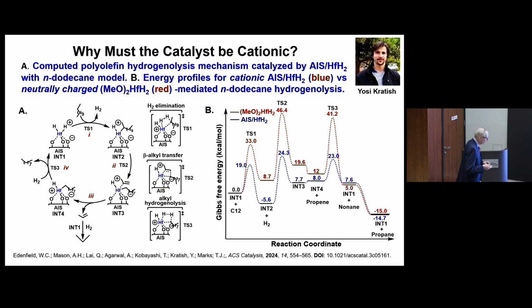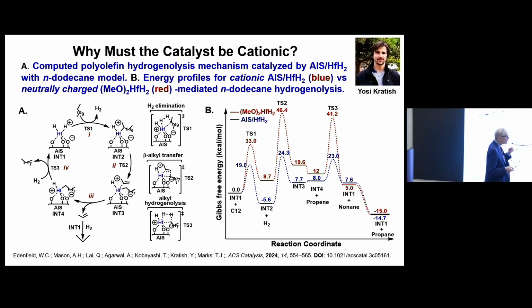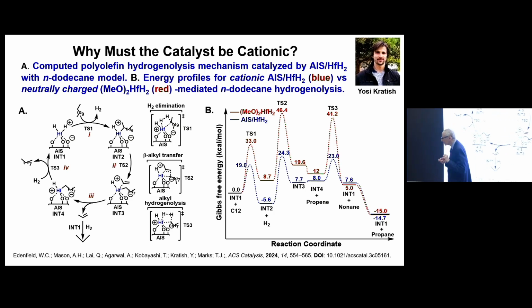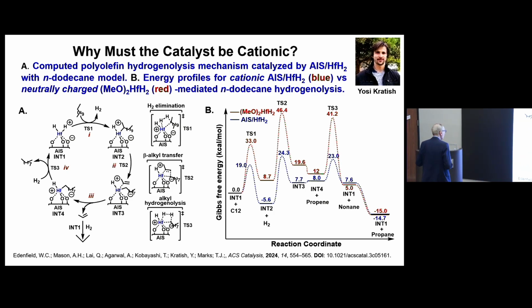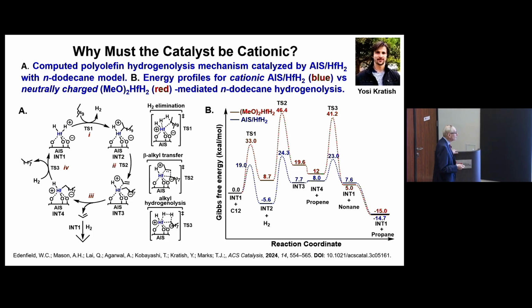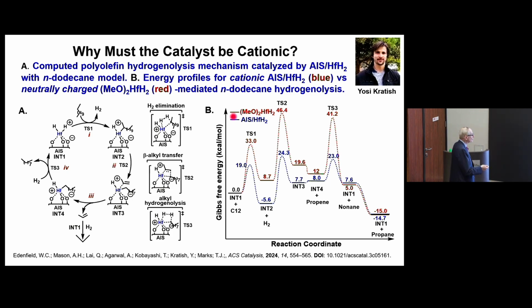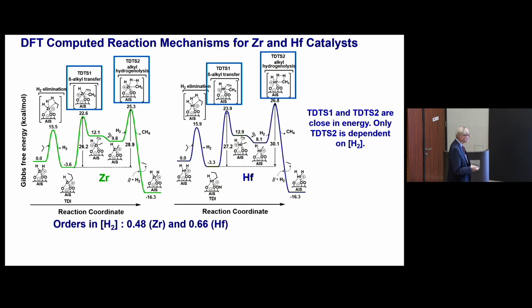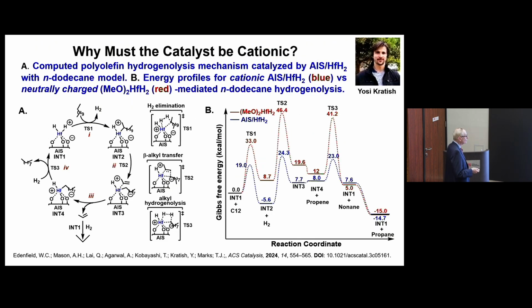But what Yossi did, you notice that all of these catalysts that I showed you are cationic. They're very strong electrophiles. So what would happen, let's imagine, here's our hafnium on sulfated aluminum. If I just had a neutrally charged hafnium with 2 methoxy ligands as the ligands. So it's neutral, so this is a cation, the blue, the red is neutral. And you can see the activation energy for the neutral compound is enormously higher than the cationic.